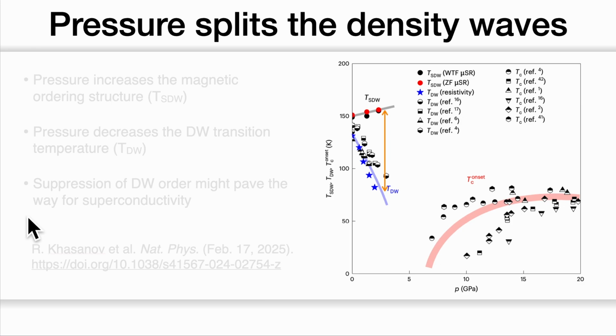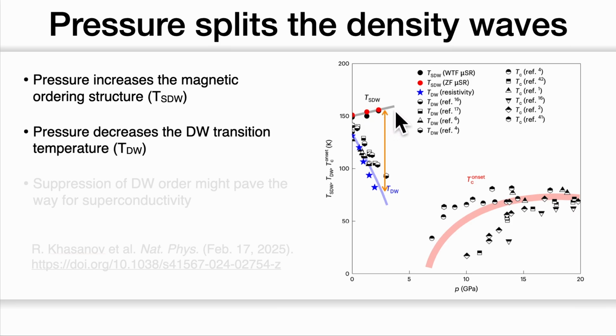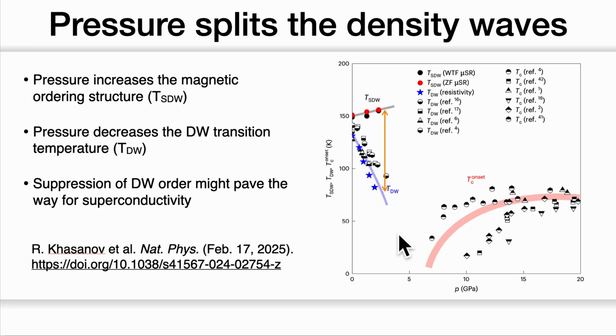Here is the summary. We see that the transition temperature of a spin density wave increases under pressure, while that of charge density wave shows the opposite trend. This shows that the spin density wave and the charge density wave are two entities with different trends, in contrast to our intuitive thought that both should show the same behavior. And understanding the separation of the charge density wave order might help us to manipulate the superconducting phase. Okay, that's all.